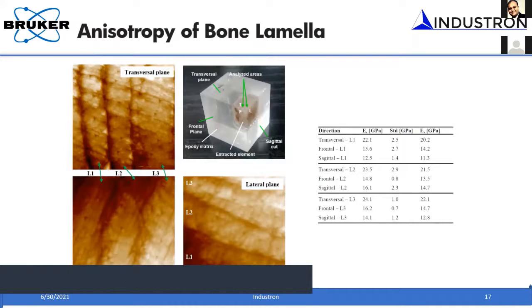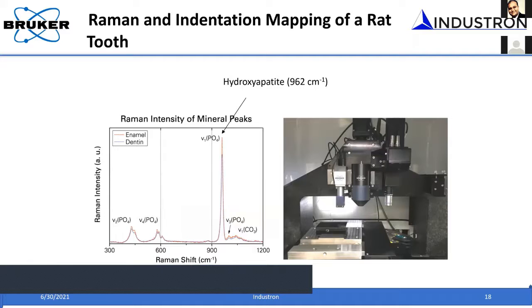For example, if you look at this table, you're measuring the modulus in 3 different directions. But you can see that at the transverse plane, the modulus is much higher compared to the lateral plane, which shows that the load carrying capacity along that direction is much better compared to the other direction. So that gives an indication of how our bone has been designed to take the load, and why this anisotropy is sometimes measured. One of the reasons that we have this anisotropic behavior is mainly because of the mineral content.